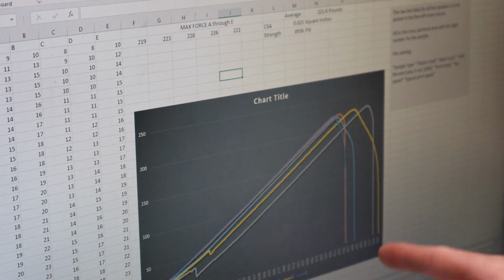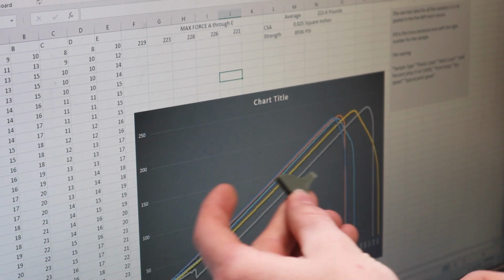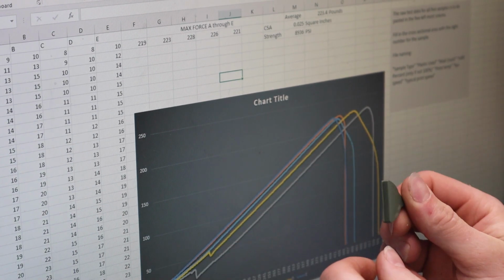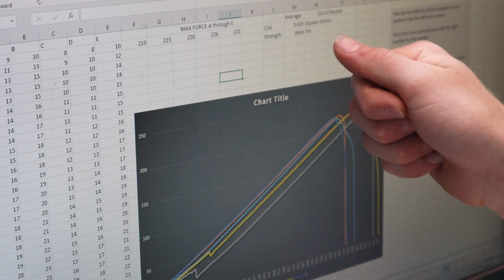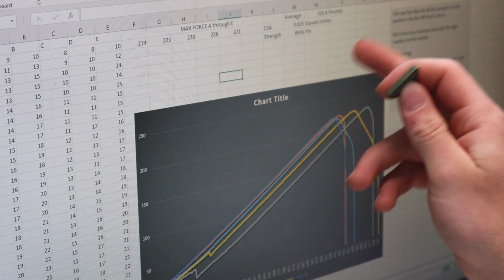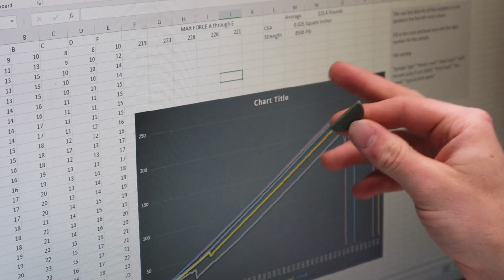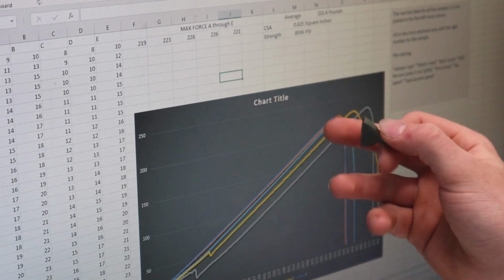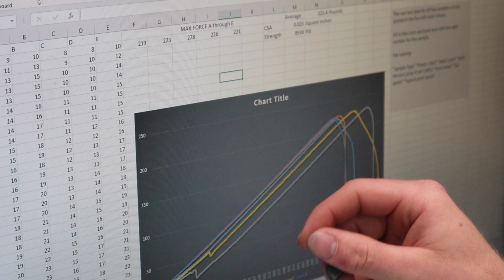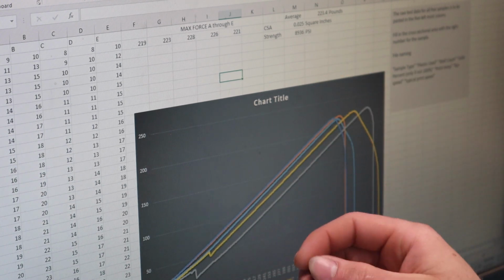Okay, so here is a quick shot of the horizontal test samples printed from the eSun PLA Plus. We were just under 9,000 PSI, which is really strong. That's actually up there as far as strength goes with prints. 8,936 is really good PSI-wise.